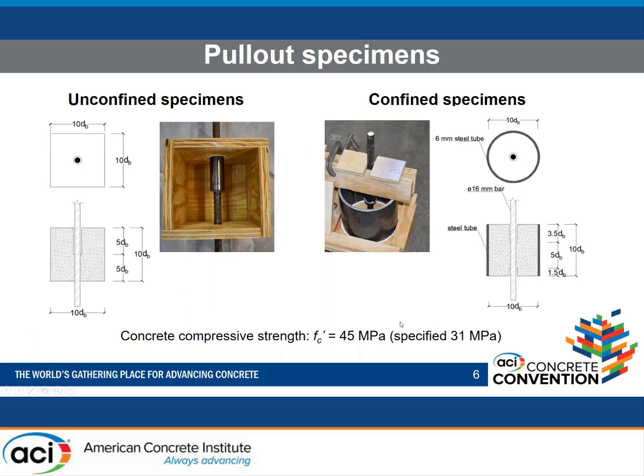As I said, we are doing both splitting and pull-out. So we started with unconfined specimens and with confined specimens. Here, this is a rebar crossing the formwork. This is a steel tube or pipe that was used in order to debond the bar over the debonded length. This is a confined specimen. We just have the formwork, while for the unconfined specimen, the formwork was essentially a steel tube which stayed there. The thickness of this steel tube was designed in order to ensure a pull-out failure. So the provided confinement was enough to ensure a pull-out failure. Here I'm showing the cross-section in both specimens, the confined and the unconfined. We have the unbonded region and the bonded region.